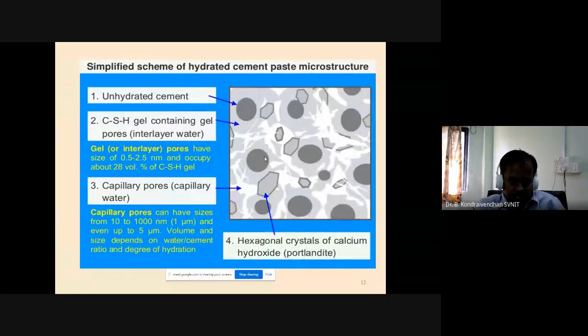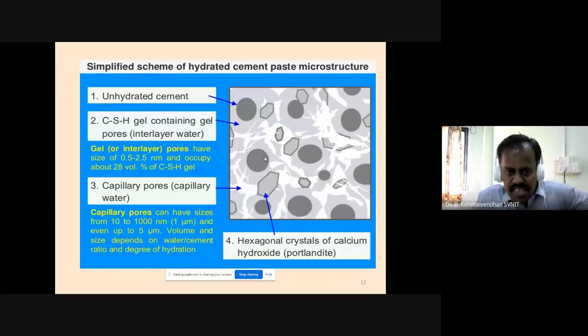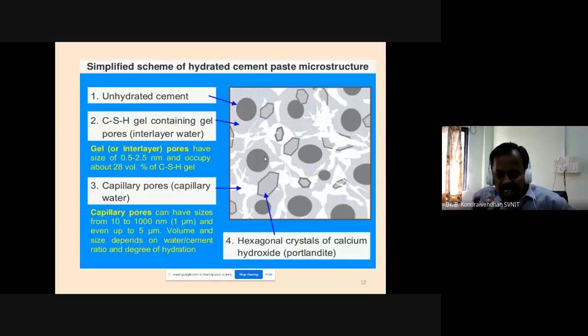And here is another picture, also taken from the same book. Here you can see the unhydrated cement particle. In the right hand side picture you can see the unhydrated cement particles, and also the C-S-H gels forming around the unhydrated cement particles. There are some gel pores there. The gel pores have a size around 0.5 to 2.5 nanometer. That's why I call the gel pores nanopores. They occupy around 28% volume of the C-S-H gels.